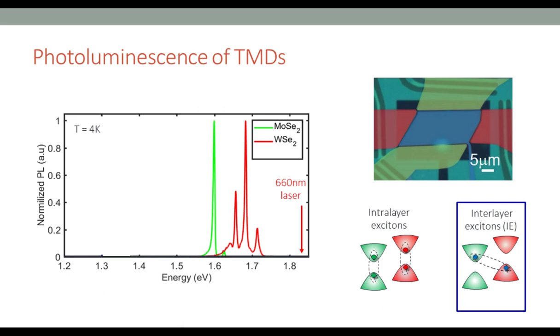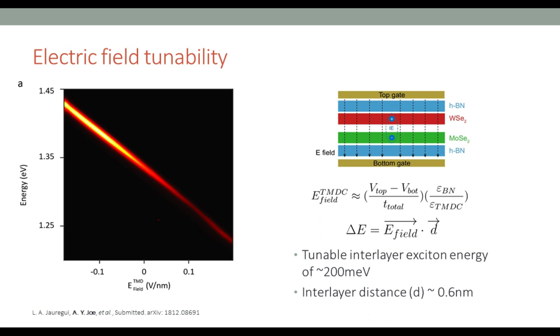You'll also notice that the intralayer, higher energy exciton peaks are strongly suppressed. This is because electrons and holes are moving into separate layers and preferentially forming this interlayer exciton. What is the most telling measurement to see if we have an interlayer exciton is that, since it's out of plane and has a permanent dipole moment, it should be tunable with an electric field. So that's exactly the measurement we do.